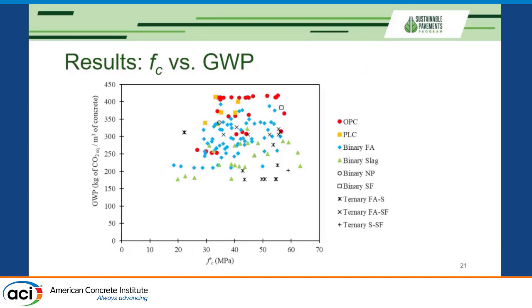Compressive strength with GWP. This is where things get really interesting, because in many LCA studies, they're grouping and categorizing mix designs based on their strength. Higher strength, higher GWP, right? No, the data shows this blob that we really didn't know what to do with. You can see here that red OPC-only mixes are kind of at the top, but generally speaking, there is no rhyme or reason to this. You can achieve any compressive strength, more or less, at very different levels of GWP.